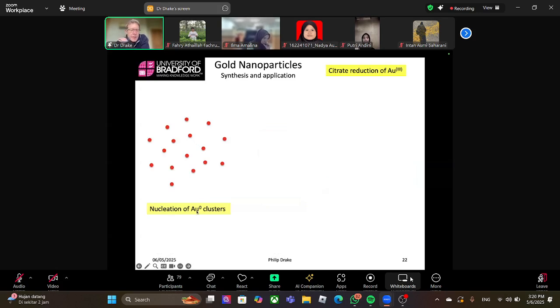So the nucleation site, you get your gold clusters, 2 atoms together, very small. The rest is still gold 3 and the citrate. That keeps on reacting to start building the nanoparticles up. So you grow the particles. You go from a small cluster of 2 or 3 atoms to final nanoparticles. These are less than 1 nanometer. These are around 13 nanometers as determined by the SPR peak. These clusters are unstable. You can't see them, you can't isolate them. They're theoretical. The gold nanoparticles are what you can see and you can characterize.